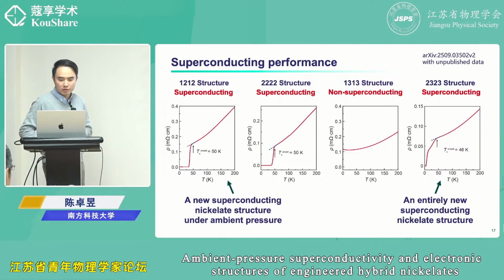In this 2-3-2-3 structure, since you have a metallic trilayer in between, the coupling between the bilayers is over a larger distance. So it's even harder for the bilayer alone to achieve global phase coherence among all the areas of the film. So the trilayer needs to be the medium for phase coherence.